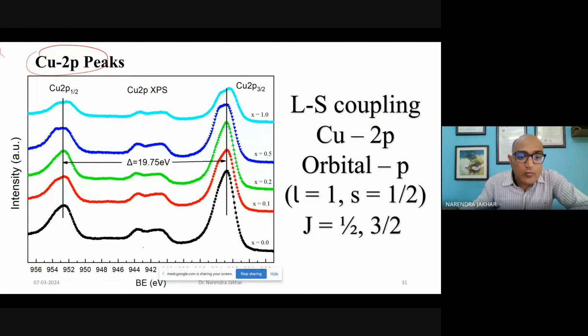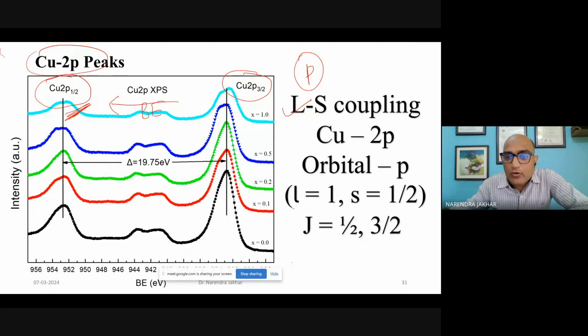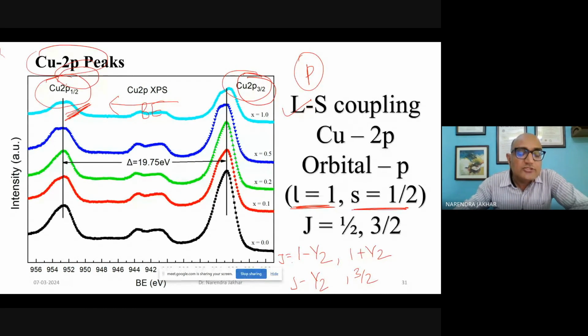Okay, so the Cu peaks are at almost 950 electron volt energy, and you can see there is a crystal clear doublet, Cu2p 1/2 and Cu2p 3/2, and you can see that Cu2p 1/2 is on the higher binding energy side. This is binding energy. Why is it so? Because of LS coupling: L is what for the p orbital? L is 1. For the electron, S is 1/2. So J can take values from 1 minus 1/2 to 1 plus 1/2. So this is 1/2, and this is 3/2. So your total angular momentum can take two different values, either 1/2 or 3/2. So this peak corresponds to J 3/2, and this peak corresponds to J 1/2.